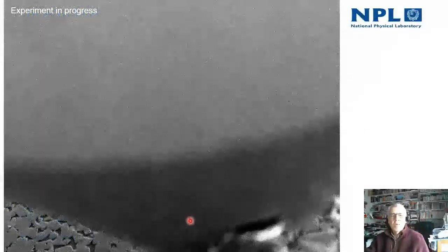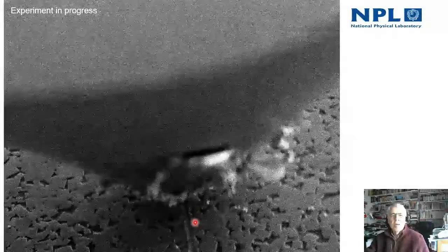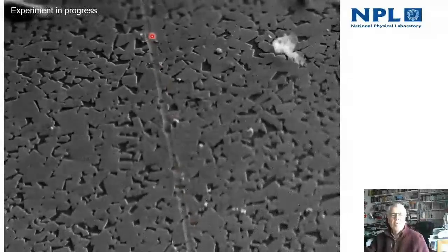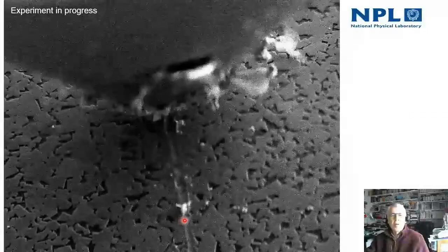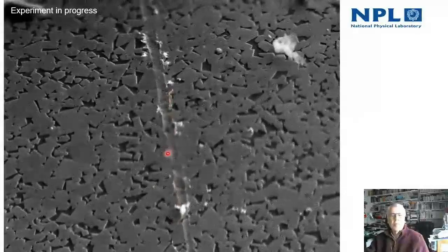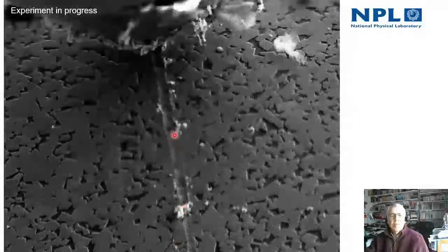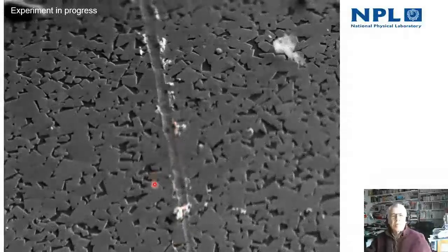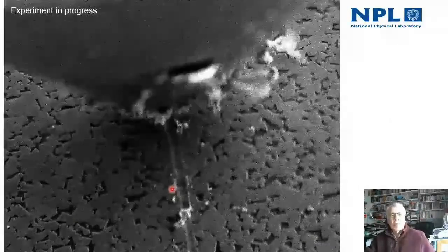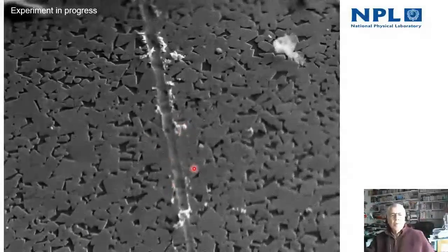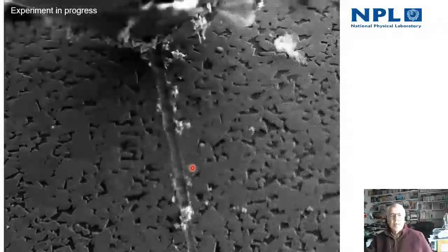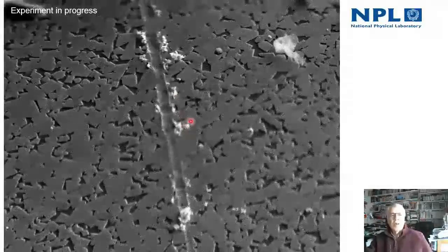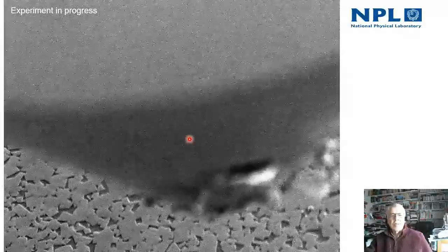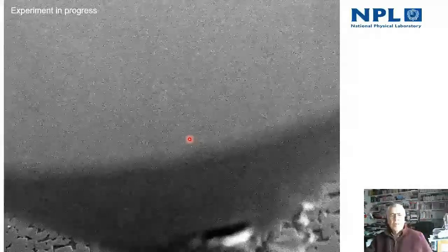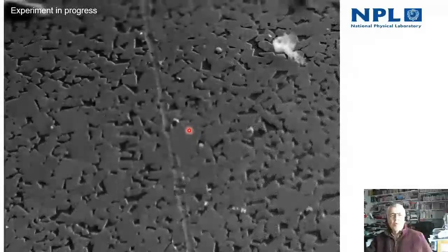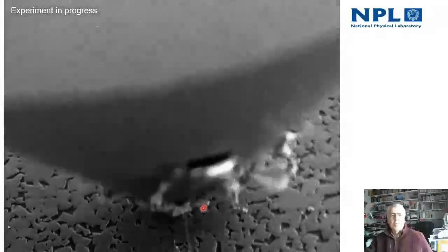So here you can see an experiment actually being carried out, and here an indenter is lowered against the sample, is then dragged across the surface backwards and forwards, and you can carry this out automatically for any number of repeat scratches. And the beauty of this is you can actually see the detail of the interaction of the indenter with the surface. In this case, you can see debris that is removed from the surface and is produced there.